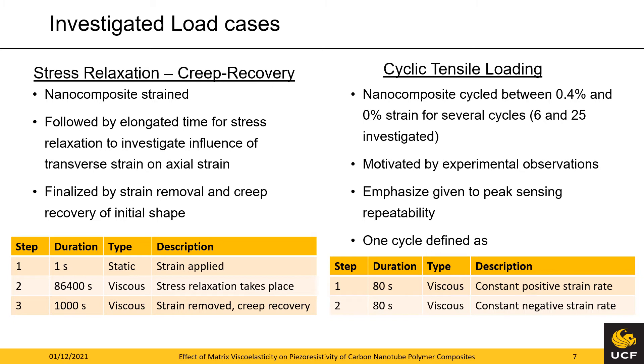The second investigated load case comprises cyclic tensile loading. The upper strain level for the epoxy was 0.4% since the fracture strain is about 2.7% for this material. The strain is applied over 80 seconds and removed over 80 seconds, and this is repeated for six cycles. The focus here lies on the repeatability of the peak sensing.